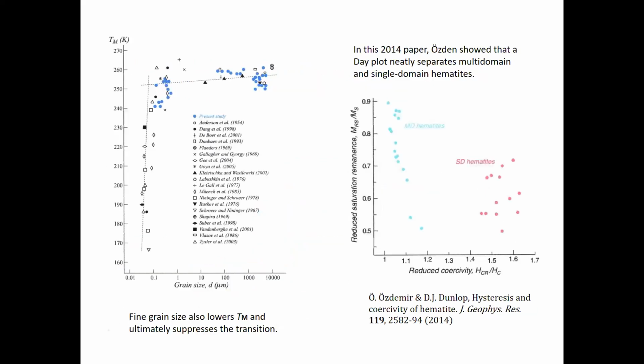And in one of her final papers, 2014, Özden showed that the Day plot sneaks in here again. This was before it was completely discredited, to show that multi-domain and single-domain hematites are very neatly separated on the Day plot. Isn't that nice? I think that's really nice. Oh, and on the left, this is a compilation of data, about half of which, in blue, are Özden's data, showing that fine grain size has the same effect. It will depress and ultimately completely suppress the Morin transition.